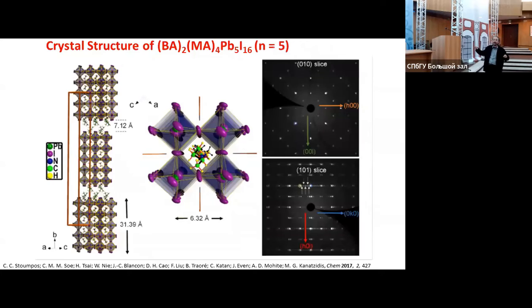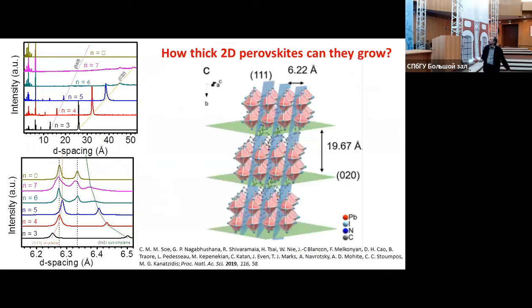And we went even further. We synthesized the 5-layer perovskite. This is how the simulated reciprocal space would look for this type of materials. And we can go even further. We were mapping how high we can go. We're looking at the limits of the system. And we found that above 5, we can actually see diffraction peaks that correspond to these higher layers. But it was very difficult to get them pure, because if you compare with the 3-dimensional perovskite here, you'll see that there is always impurity from the 3-dimensional phase. To some extent, these materials become 3-dimensional. And they are impure, so it is difficult to acquire the properties of these materials.